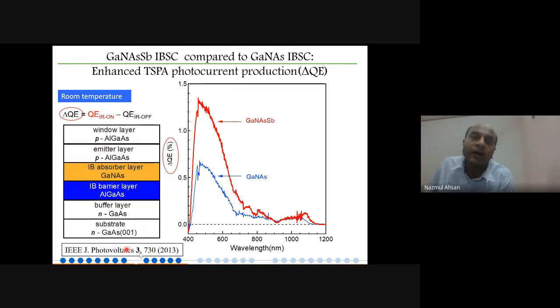And this sample we made by molecular beam epitaxy on a gallium arsenide substrate. For example, here I have an N-type gallium arsenide substrate, and there I have a gallium arsenide buffer, and then I have an aluminum gallium arsenide wide bandgap barrier layer. Then I have gallium nitride arsenide, the intermediate band material. Then I have another P-type wide bandgap material, and then a window layer. I told you the semiconductor solar cells are a sandwich of p-n junction. So we have p-n junctions on the backside and foreside, but in between we have intermediate band material. And with this kind of material, we have demonstrated that we can generate current due to 2 photon absorption.